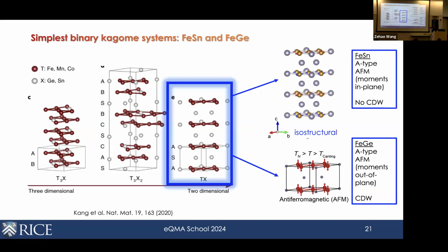And both iron tin and iron germanium belong to this structural family. They're isostructural, and they're both made of stacked iron Kagome layers. And they both have a magnetic order above room temperature, and the form of the magnetic order is that within the Kagome plane, they're both ferromagnetic, and then along the stacking direction, they're both antiferromagnetically aligned. So this is the A-type AFM order. The only difference is that the moments are in plane for iron tin and out of plane for iron germanium.